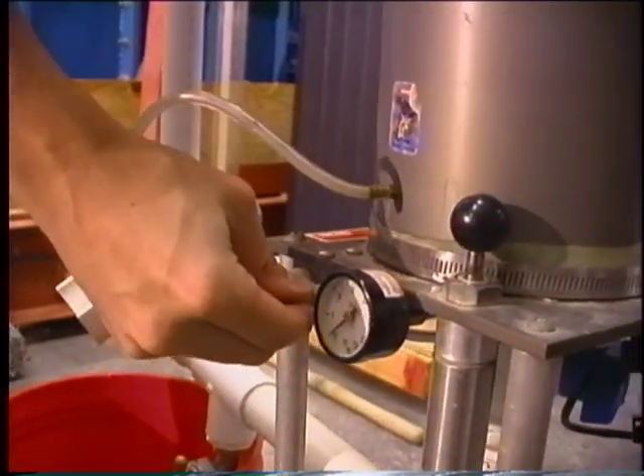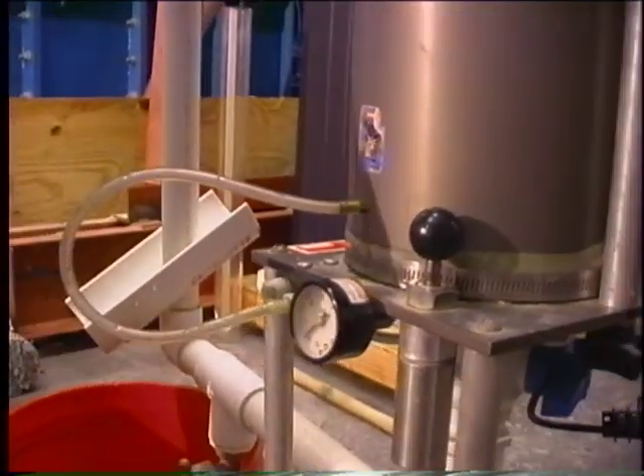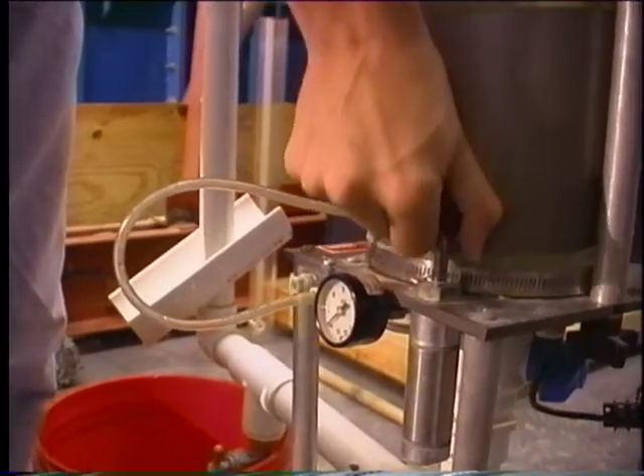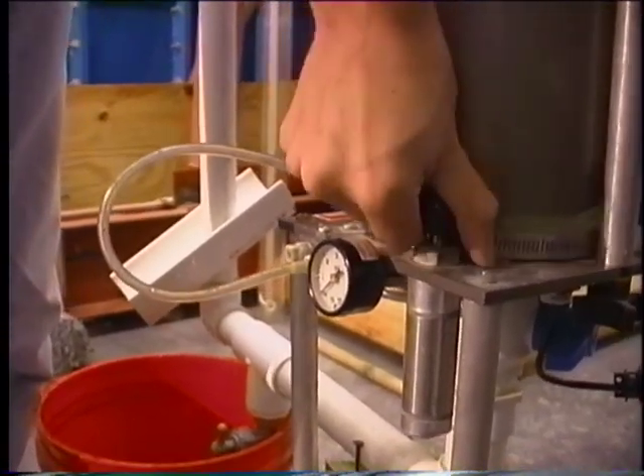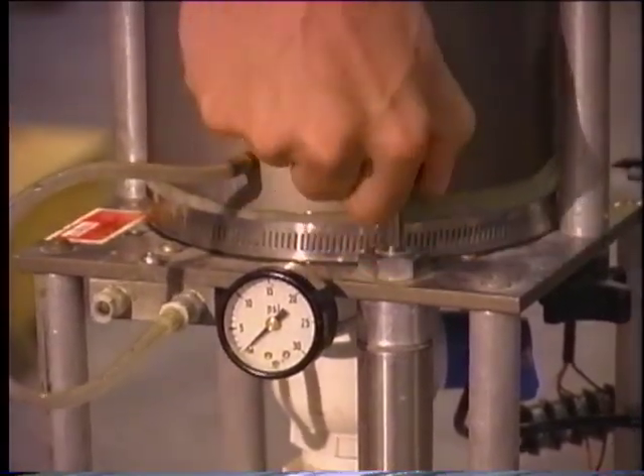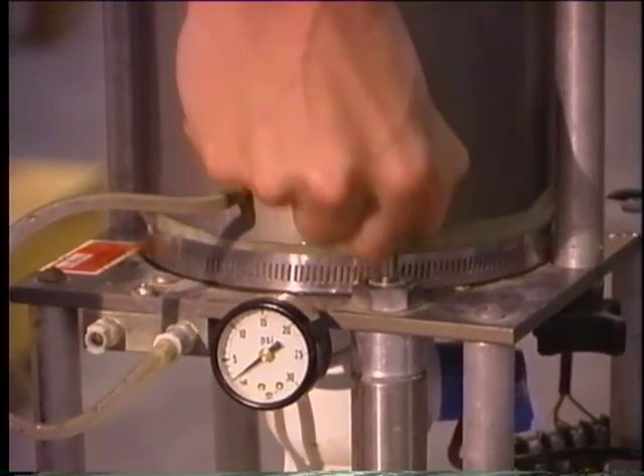Next, place the pressure line on the pressure nozzle. The sample holder should be pressurized to at least 5 pounds PSI. This pressure prevents water from flowing along the side of the sample, as water must flow through the sample. If water is able to flow down the side of the sample, the data will be inaccurate.